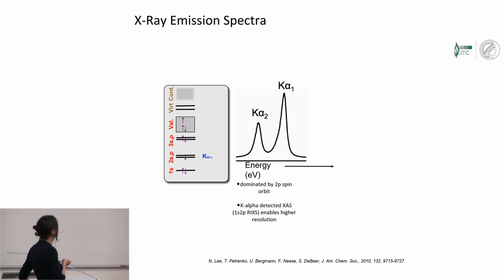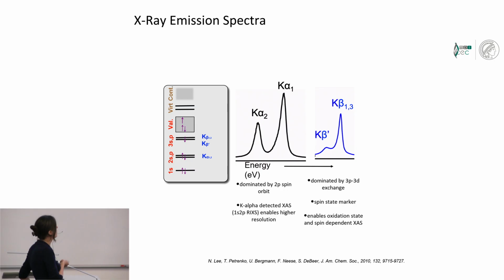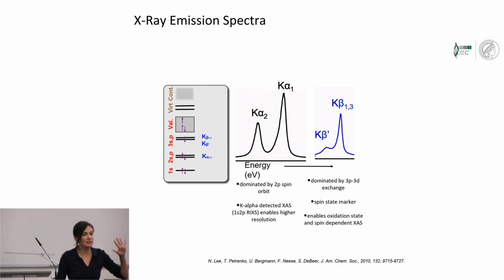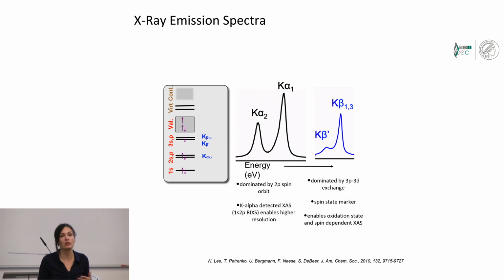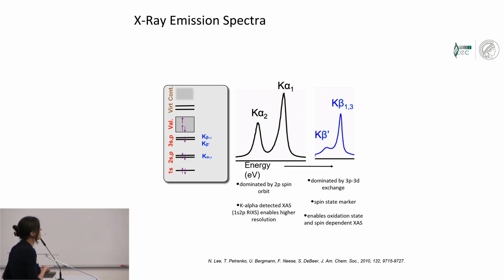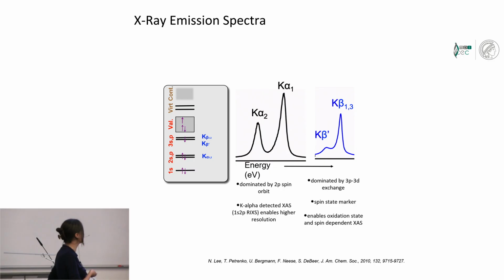The other thing we can do is look at a 3p electron refill the 1s core hole. This is an order of magnitude less likely, but because we've created a 3p core hole, which is energetically closer to the 3d levels, these are final state spectra that are dominated by 3p 3d exchange. That means if I have a lot of unpaired electrons in my d manifold, the spectral shape reports on the number of unpaired electrons. And it has also been used to enable oxidation state and spin-dependent X-ray absorption, as well as XES. Sophisticated and challenging experiments, but possible in certain cases.